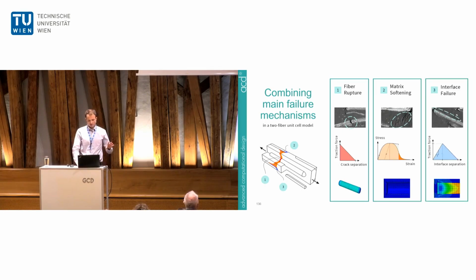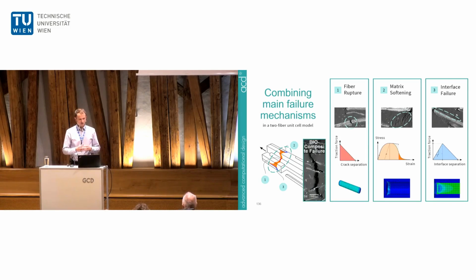And all those damage mechanisms act together, some more and some less, depending on the individual components, until the biocomposite is fully torn apart. And we now have a model at hand to fully simulate such post-crack behavior of biocomposites, which has actually never been done before.